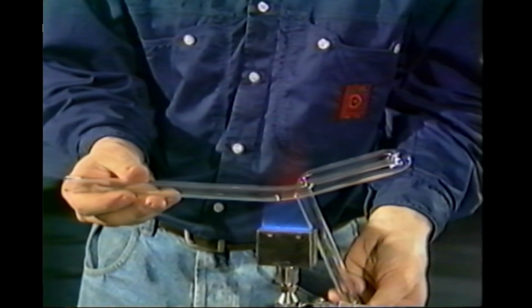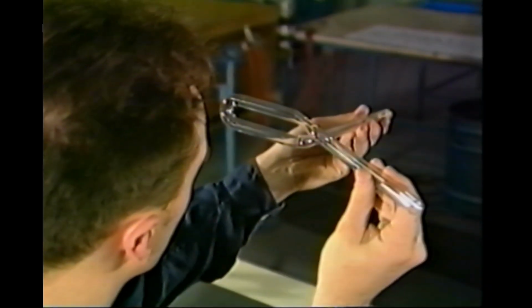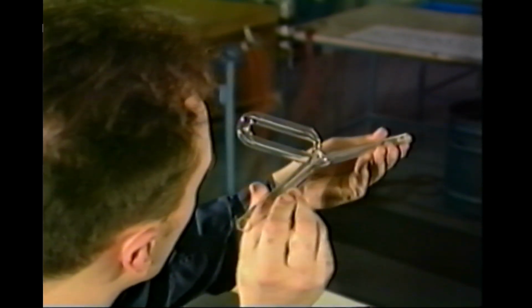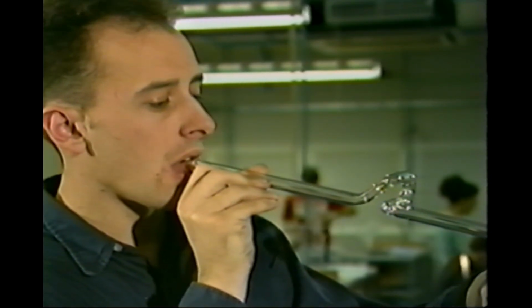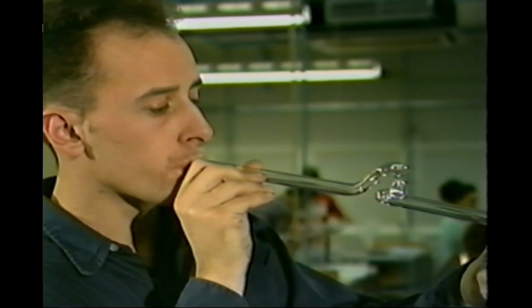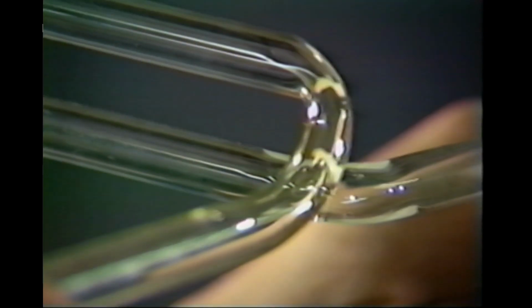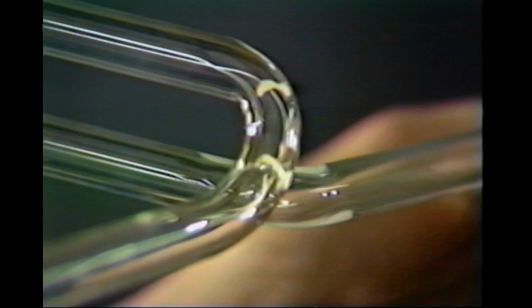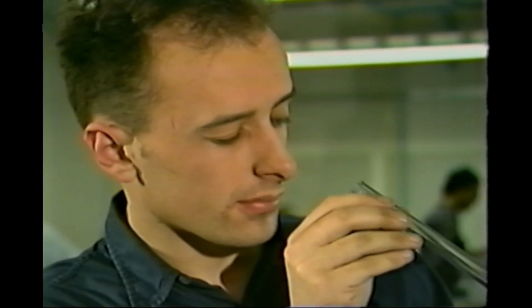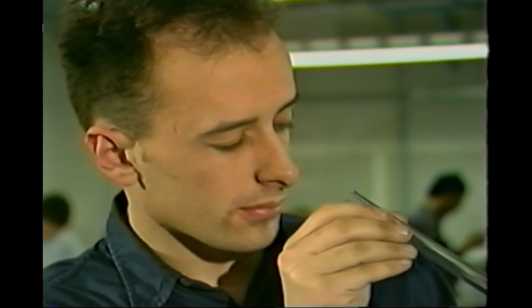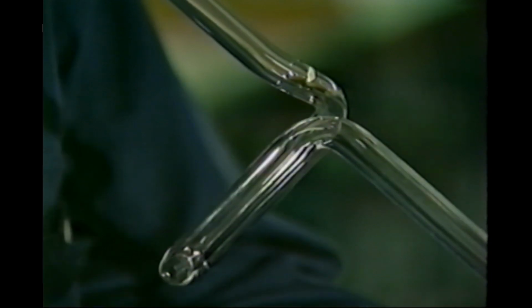When melting is complete, raise the tube to eye level, keeping it horizontal. Allow the heated portion of glass, the right sidearm, to drop down 3/4 of a diameter, then bring this sidearm around in line with the mouth, and at the same time, roll the tube through the fingers clockwise. When both sidearms line up, blow to restore diameter to bend area. Finally, by sight, check alignment of both straight legs and ensure that the drop bend is the correct depth.